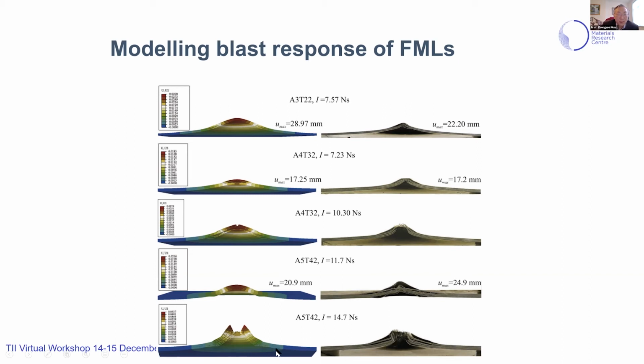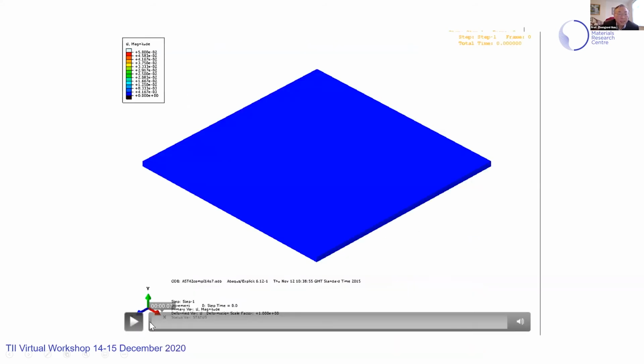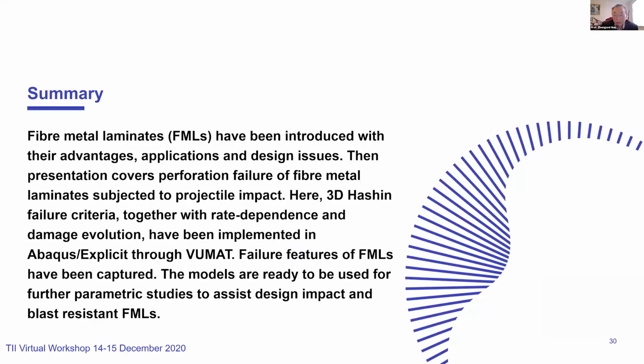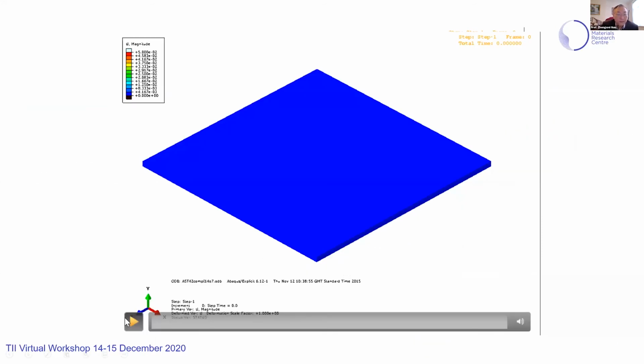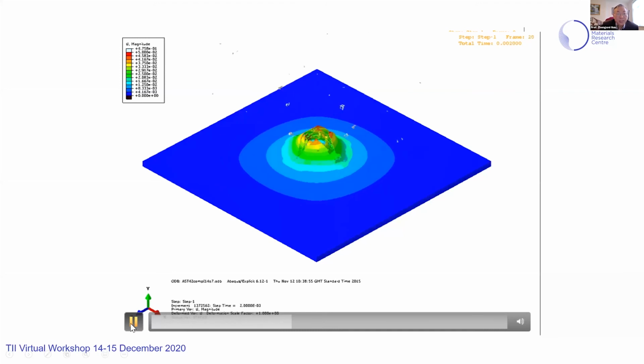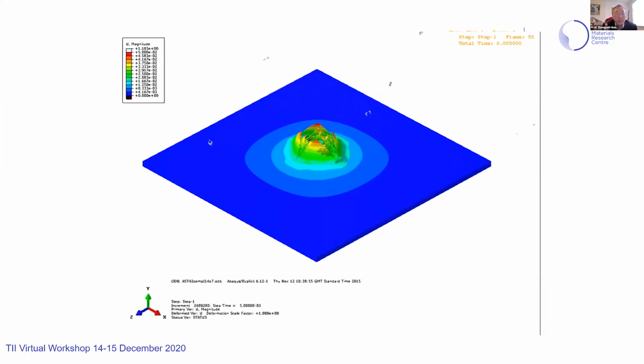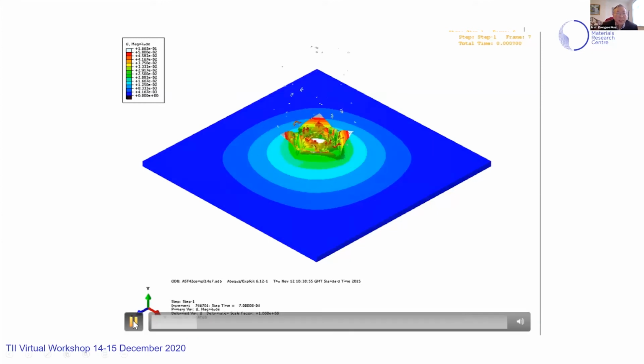So 5-4 is like a puncture failure, because the fiber metal laminate is relatively thick and we have a higher explosive mass. So this animation again shows this failure simulation. You can see it's a relatively localized perforation failure.